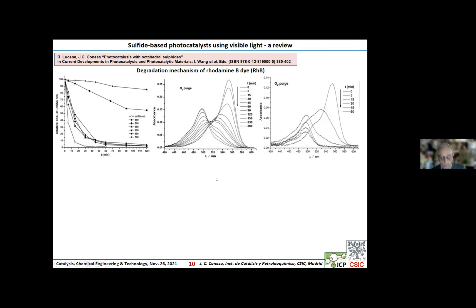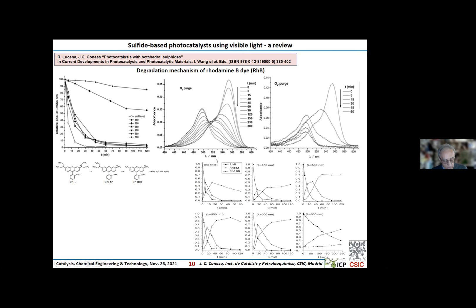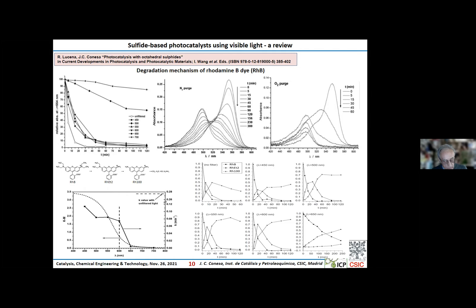By carrying out a principal component analysis, we were able to see that there were only three components in the degradation, and by comparing with literature data we could verify that the mechanism is as shown. The fact that with oxygen bubbling the reaction works much faster than with nitrogen bubbling means that the first two steps depend mainly on the more aggressive OH radicals, but only with oxygen bubbling can the degradation be finally completed, requiring superoxide or OOH radicals for the final step. The principal component analysis confirmed that the wavelength dependence was that of indium sulfide, not that of the absorption by the rhodamine B dye.